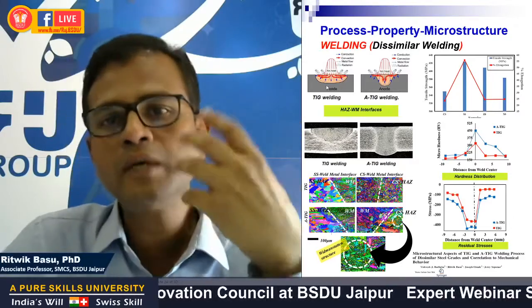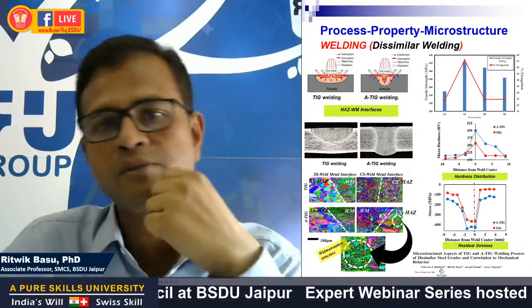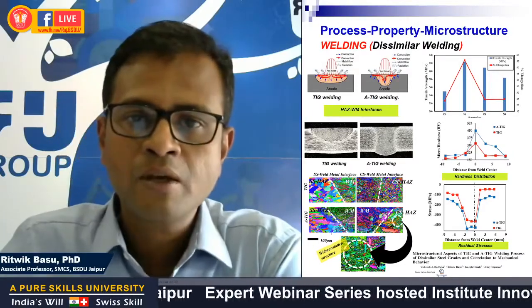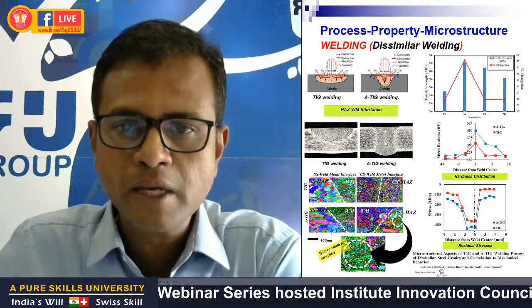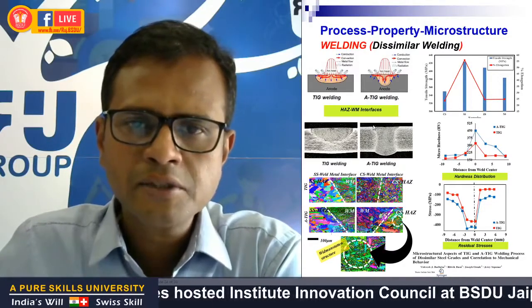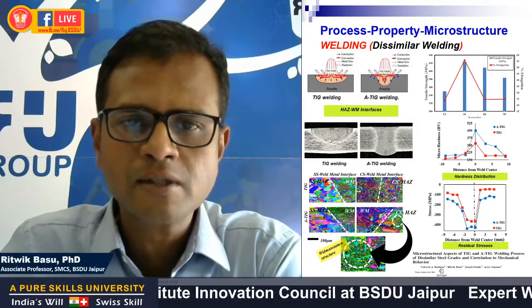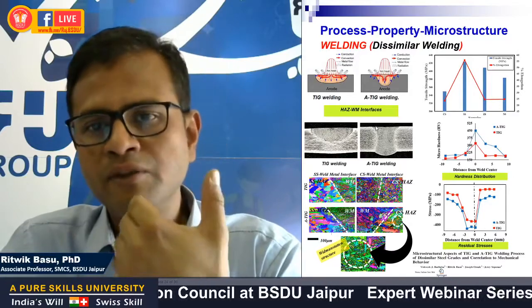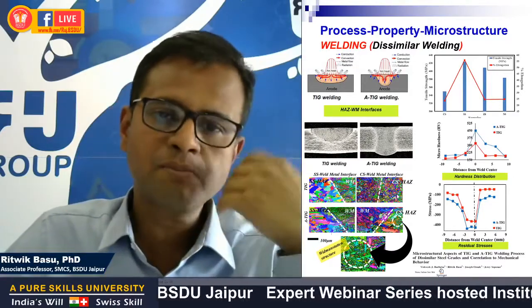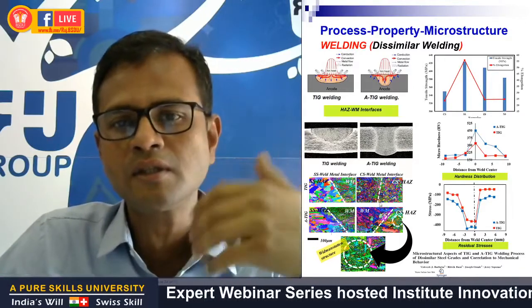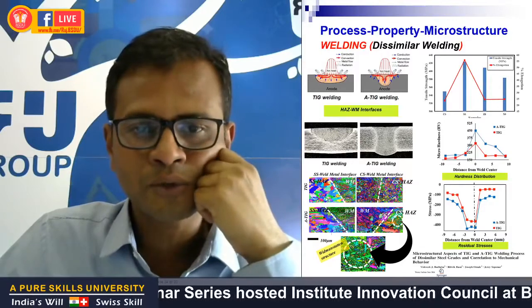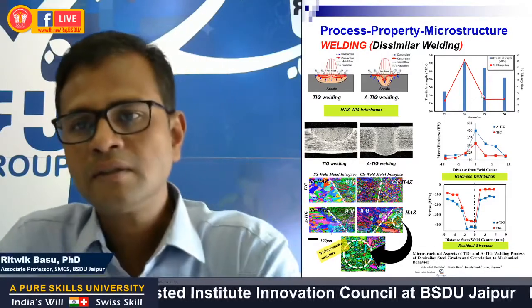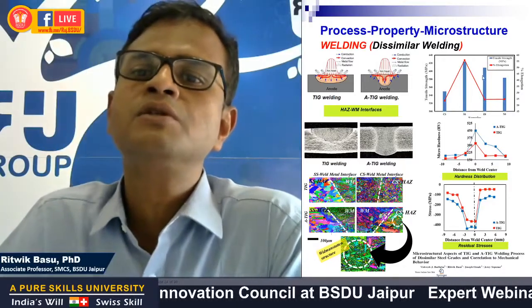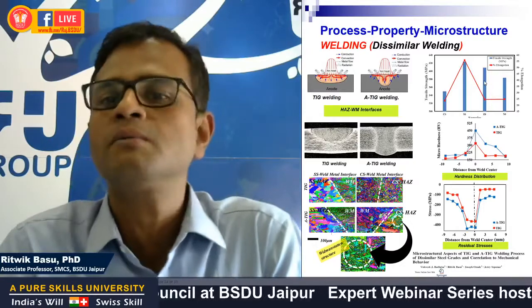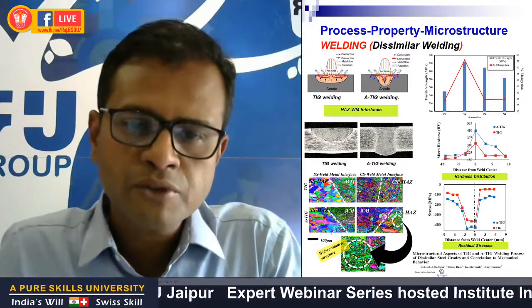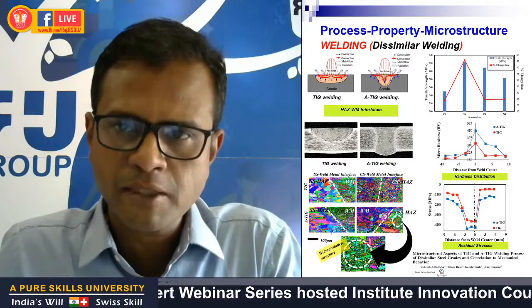So therefore, the nuclei of the austenite grains that are formed grow by advancement of the planar interface for a longer duration of time. While in the case of A-TIG welding, the weld pool, as you could see, is much deeper and narrower, and the arc energy does not heat up the surrounding regions to the same extent as in the case of TIG welding, and therefore the weld can cool down much faster. So this is partly speculative of why these differences in the microstructures could be observed through TIG and A-TIG welding. Again, the relatively high strength of the A-TIG welded specimen could be attributed to the higher in-grain misorientation in the microstructure, and also due to the formation of the Widmanstatten structure that introduces significant grain refinement.